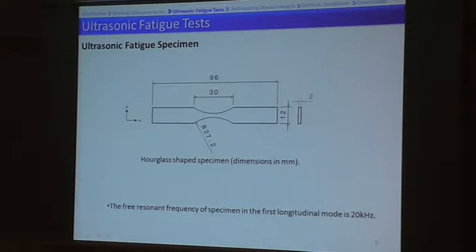In order to do the ultrasonic fatigue tests, we designed the fatigue specimen as you can see here in this picture. It's an hourglass-shaped specimen with the dimensions shown in this picture. It was designed in such a way that the free resonant frequency of the specimen in the first longitudinal mode is 20 kHz, equal to the frequency of the testing machine.